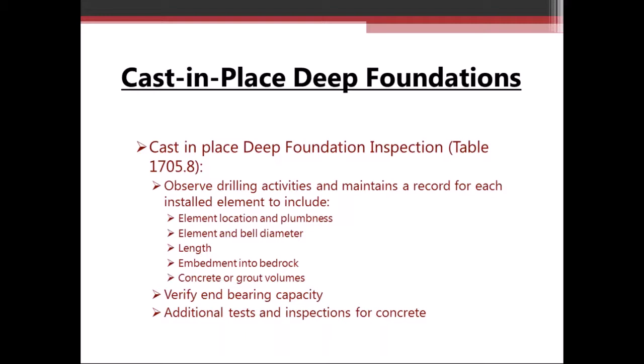Cast in place deep foundations. These typically consist of drilled concrete piers, micro piles, or auger cast piles. And with these, the inspector is going to monitor the drilling activities and maintain a record for each one. Verify the location, the plumbness, verify the diameter of the piles, the length.